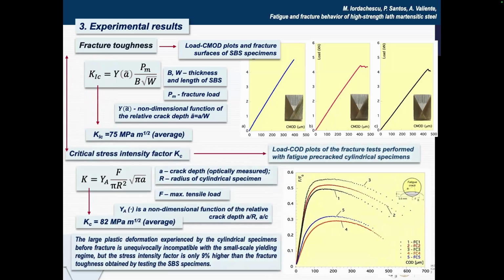Now, related to critical stress intensity factor Kc, which was obtained after fatigue pre-cracking, practically by fracturing the cylindrical specimens, as can be seen in this graph, the plots are given in load versus crack opening displacement. We used this other equation, and practically from these 5 tests, the average of the critical stress intensity factor is 82 megapascal square root of meter.